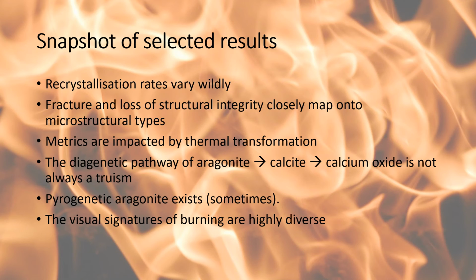Apologies to any chemists. And sometimes pyrogenic aragonite formed, and this is a really mercurial one in the literature because aragonite's known to not be particularly stable. It transforms to calcite. This is a truism. But the fact that you should get aragonite forming in a fire circumstance, which is what pyrogenic aragonite is, is something that's not fully understood in any branch of science. You get the formation of these tiny needles of aragonite, and she certainly noticed that in some of the experimental samples that she ran.